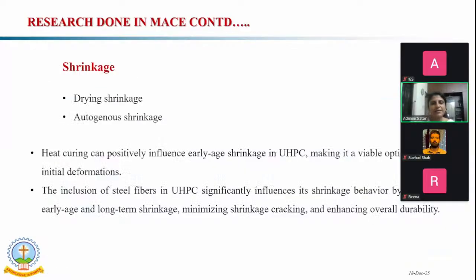When we considered shrinkage, we considered only the drying shrinkage and the autogenous shrinkage, with a specimen of 280 by 20 by 20 mm. In that case, we considered heat curing and normal curing, and also the inclusion of fibers and without fibers, to see the effect in the case of UHPC.